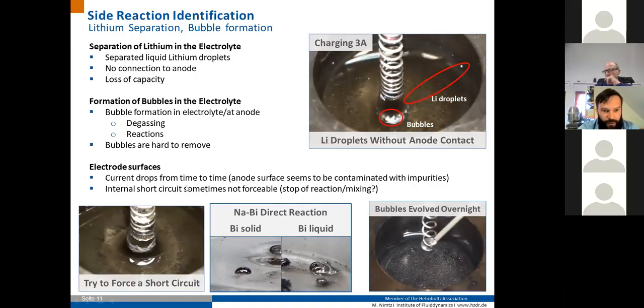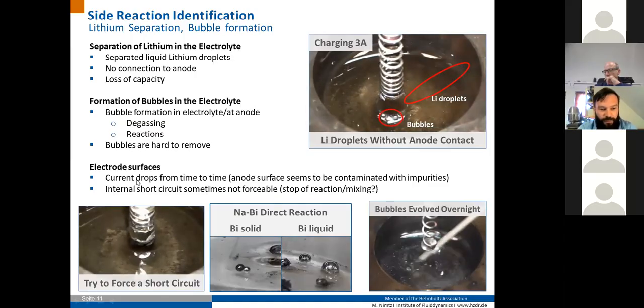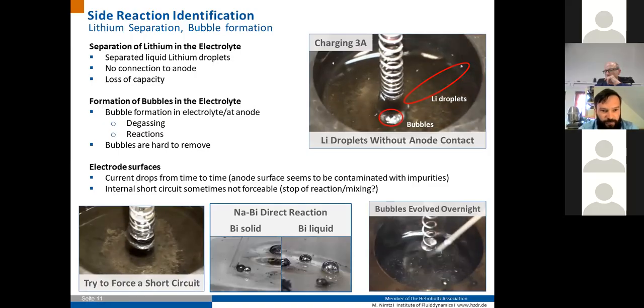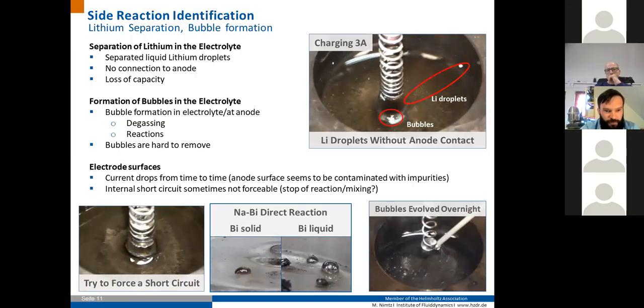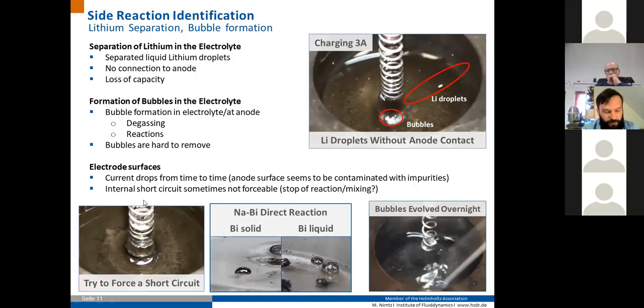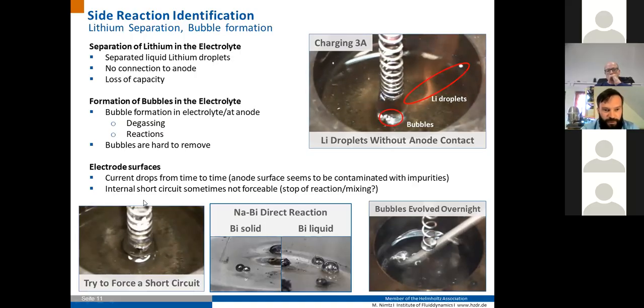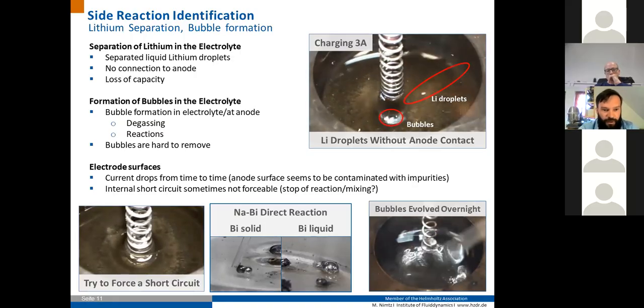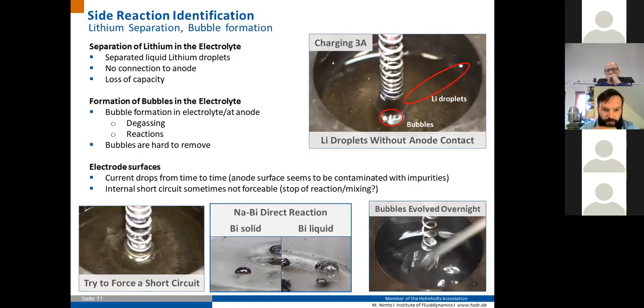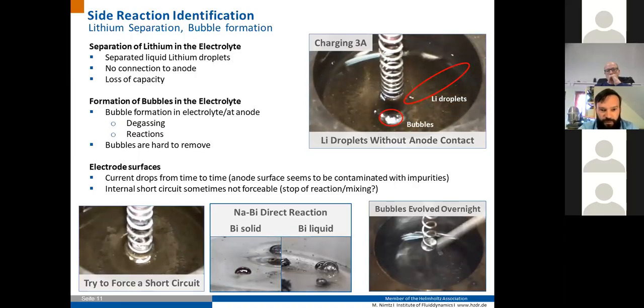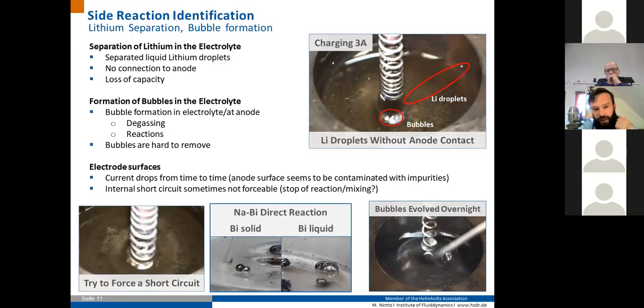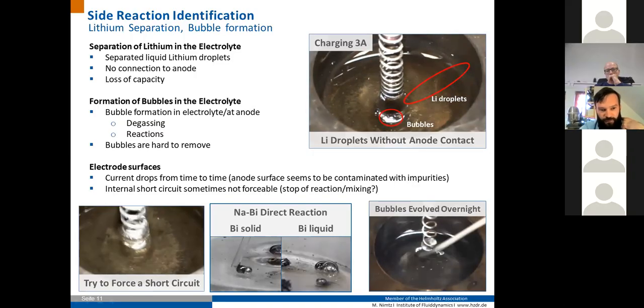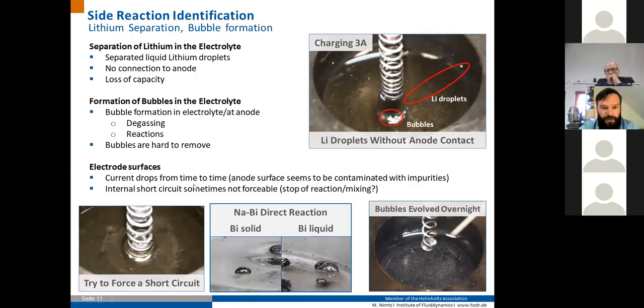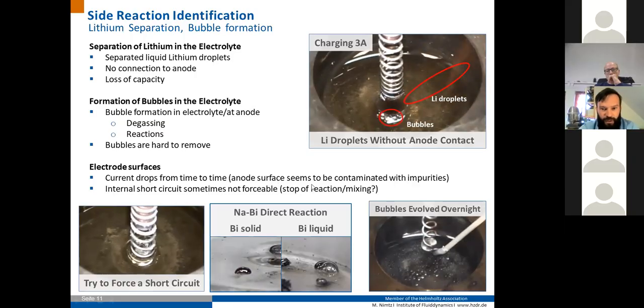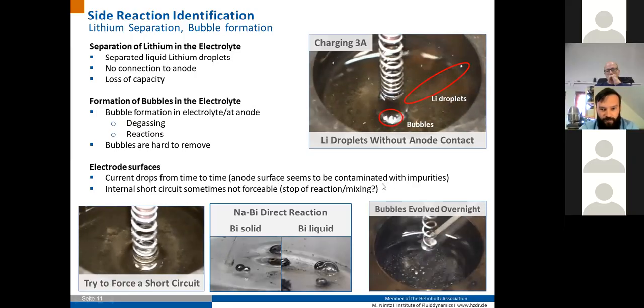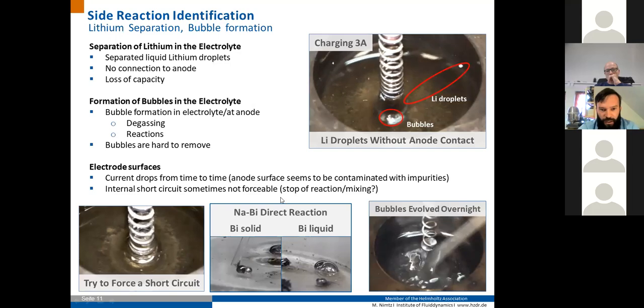Other observations we made were, for example, current drops during experiments, which means the measured electric current going nearly to zero from time to time. This was especially at times where the anode surface was covered with impurities. And